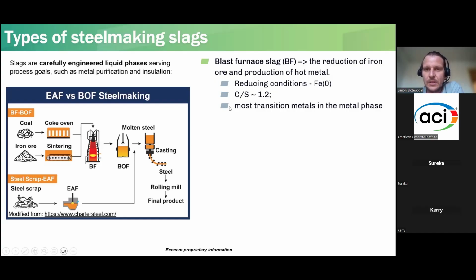If we start with blast furnace slag, from a slag use perspective, it is important to note that it's produced under reducing conditions, so iron remains in the metal phase and will be separated off. The calcium-silicon ratio is usually something around 1.2, and the transition metals, apart from titanium maybe, mostly go into the metal phase, so we don't have to deal with them.